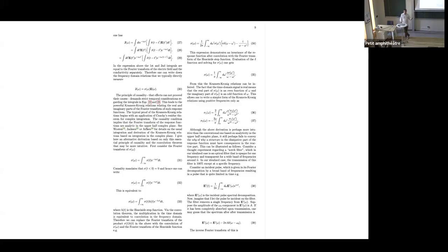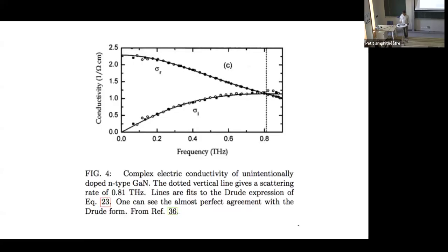Very often, and particularly in time domain terahertz, what we do know is the full complex response, but in a limited frequency range. So we know the real and imaginary parts in some frequency range, and we want to learn about something outside that range, and that's something which is also possible with Kramers-Kronig. Again, the linear response functions are the simplest we have, and they're powerful, for these kinds of reasons. I'll talk about this a little more in my talk later today.